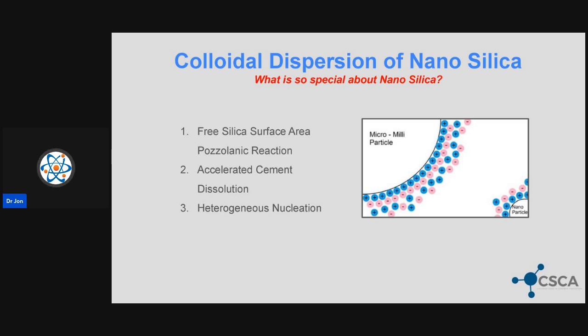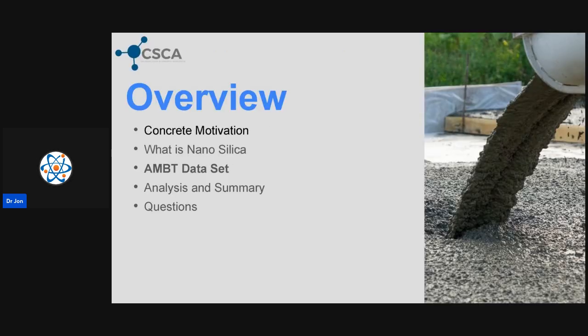And the last piece, what makes nano silica different from other particles in the micron realm, is something called heterogeneous nucleation, which is a very fancy way of saying that because we have a very small particle, it has a very small force field, and therefore other things will want to grow on that particle because of said smaller force field, or electrical double layer. I illustrate that here with my micrometer-sized particle versus the nanometer-sized particle on the right. Those change the force field.